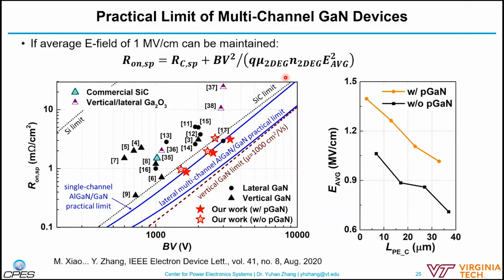But the baseline is that in all our current high performance devices, we actually use multi-channel wafers without intentional doping. So all the channels are polarization induced, and probably the origin of the 2DEG is similar to that in the single channel device, say, from the surface donors. And the limit of the increased channel devices, I think that's an open question.